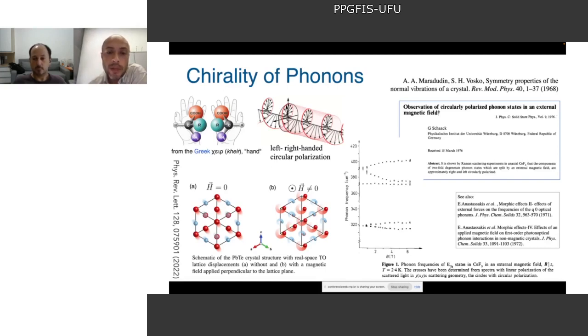Also in this talk, I will only show results for transverse optical phonons, which can couple to light. Here I have an example of a TO phonon in lead telluride, which is one of the materials that I want to present today. Here you can see that these red and blue spheres, in the absence of magnetic field, oscillate in this TO phonon mode in a linear direction. So they move oppositely, one towards the other, along a linear direction. However, when you apply a perpendicular magnetic field, then these ions perform circular orbits, which are also in opposite senses. And this is a chiral phonon for lead telluride.